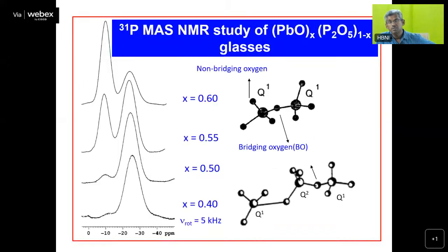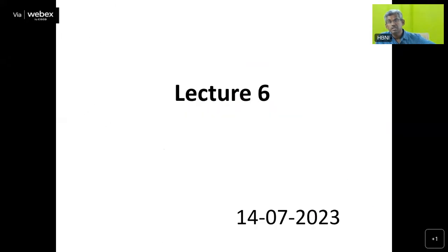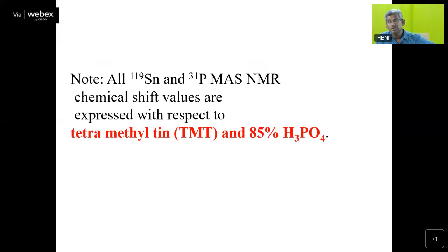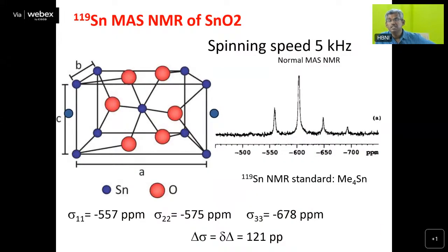But the line shape, the peak positions, etc., you will get from how much is the shift in the chemical shift value. For example, in the case of aluminium gallium phosphate, we told that around 5 to 6 ppm shift is there with the replacement of each aluminium with gallium. Similarly, around 7 to 8 ppm shifts are there with each tin which is getting replaced by titanium. So we have 11 configurations.